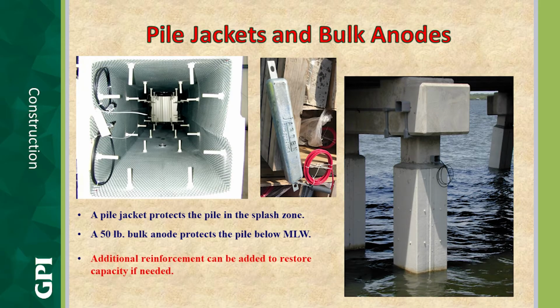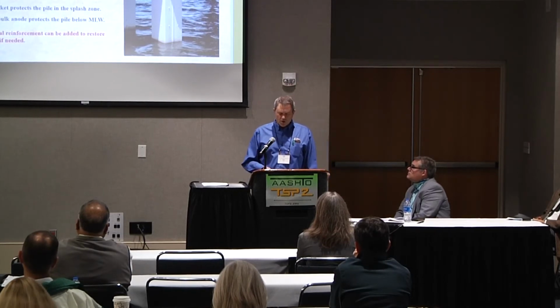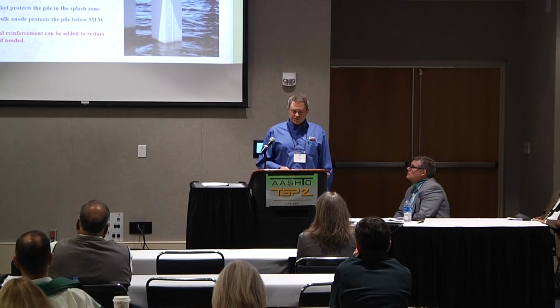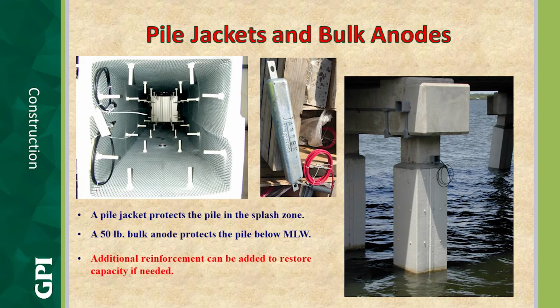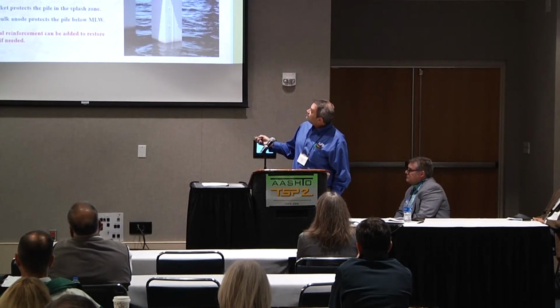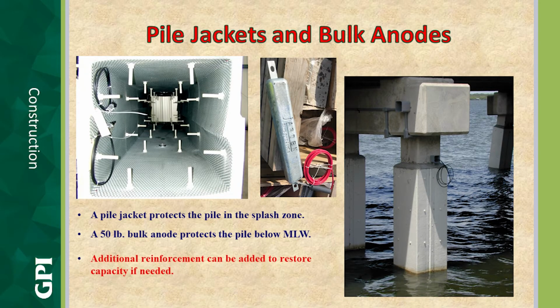The picture on the left is of an off-the-shelf pile jacket fitted by the manufacturer with spacers that create an annular space for the grout, and a zinc anode expanded wire mesh, and it is pre-wired for easy connection to a junction box for system monitoring. I want to point out, these are just off-the-shelf jackets. Once the jacket's installed, it's fully filled with cementitious grout. The picture on the right is of an installed jacket that once the wiring is finished will be complete. The bottom of the jacket should remain submerged, and the top of the jacket is traditionally about 6 feet above high water. So the pile jacket protects the pile in the splash zone. We've got a 50-pound bulk anode submerged and wired up into the junction box, and we can add additional reinforcement if we need to restore capacity.